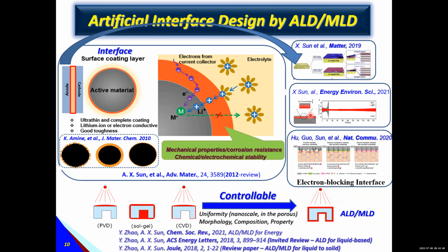Our group has worked on this for many years, developing the ALD and molecular layer deposition methods. For example, for lithium metal, we need to control the artificial interface. We use ALD and MLD hybrids to control it. Recently, we're also using gradient coatings to protect the lithium metal, and we can also control the electronic conductivity of the interface. So from here, we can see ALD and MLD play a very important role as artificial interfaces.